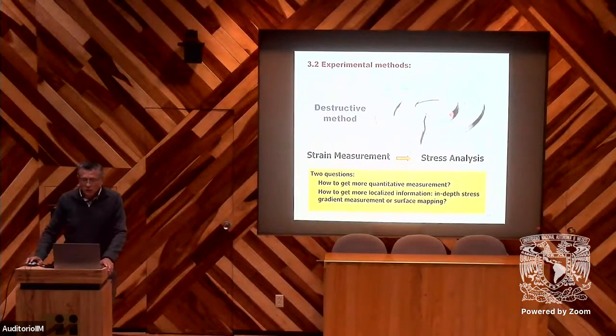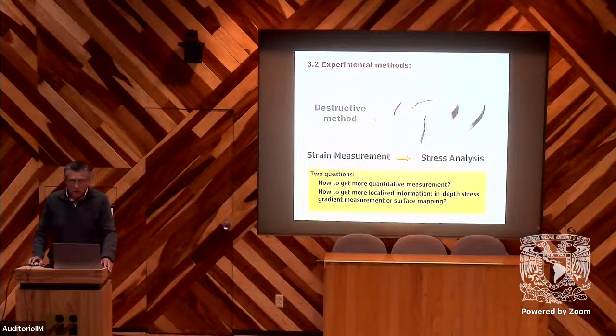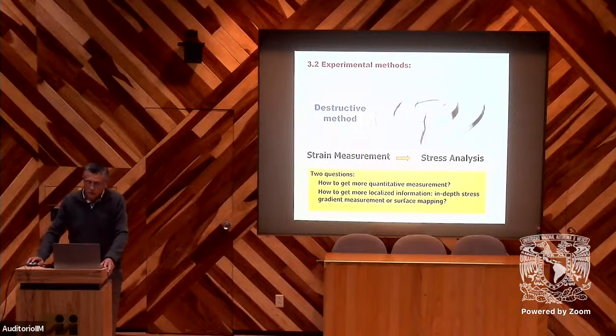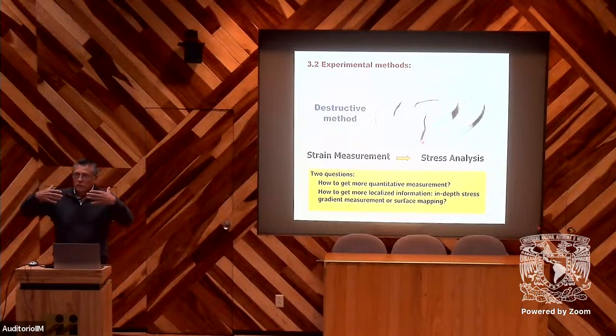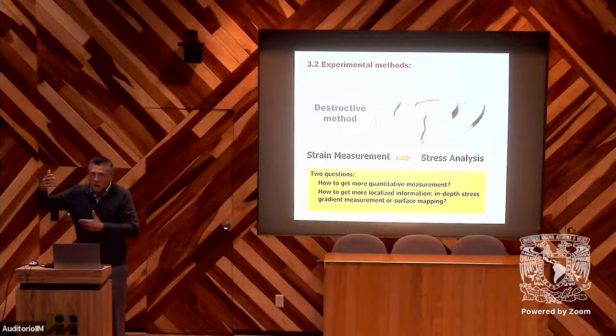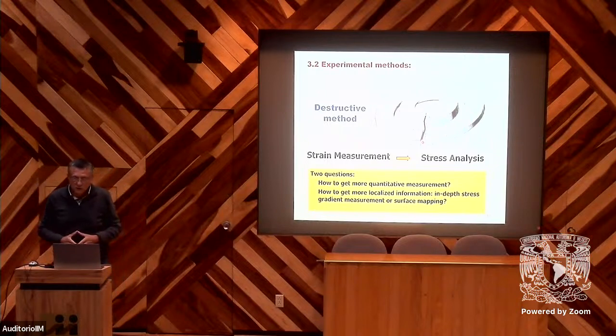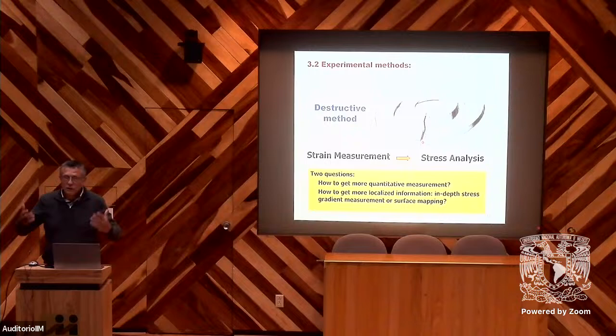So now, what about the experimental methods to measure residual stresses? A very simple method used in the automotive industry is this one. For example, applied to a brake disc, we just make a cut and we see the opening or distortion of the disc after cutting. And from this, we can determine if there is a high level of stresses or low stresses. So this is very macroscopic and we have an average of what happened in one part.